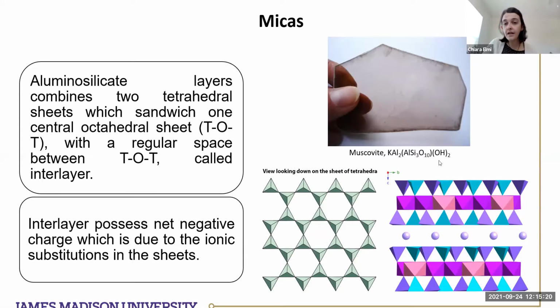Okay, so you see that they have very long formulas, and you see that the silicon can be replaced by aluminum. Sometimes the aluminum in the octahedral layer can be replaced by magnesium or iron, and also the cation in the interlayer could be potassium, calcium, or sodium. So they have similar charge, but depending on the substitution that you have in the TOT, you can have a different set of cations in the interlayer.